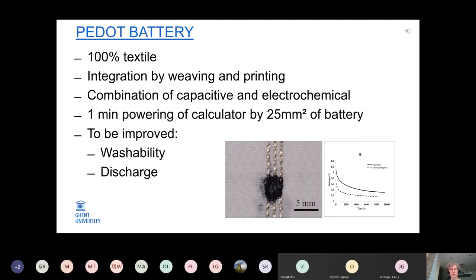At the end of the research, the washability had to be improved, and the system is subject to spontaneous discharge, which is due to the conductivity of the PEDOT:PSS. So we will try to solve this by reducing the conductivity of the PEDOT. And washability can be improved by coating the PEDOT:PSS, but of course, when we go to larger surfaces, this is not what we want to do, because then this changes the thermal comfort of the textile materials.